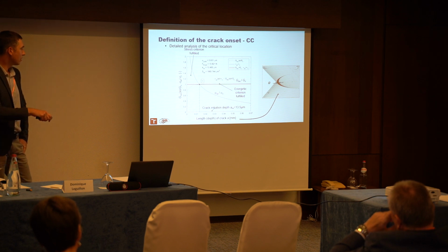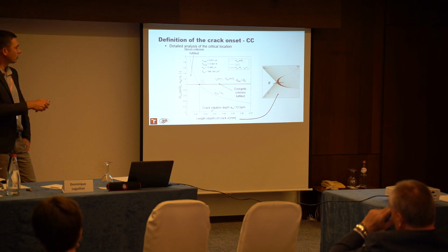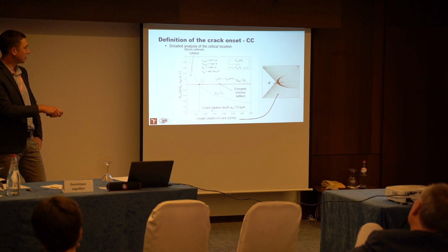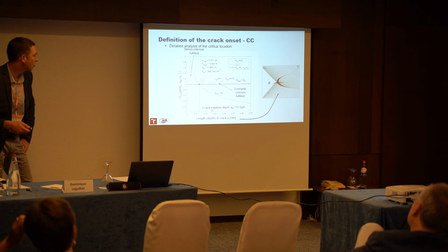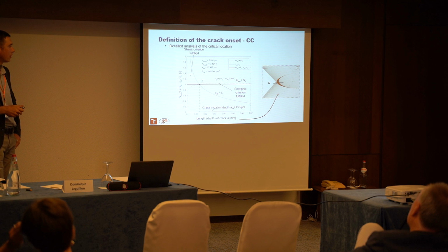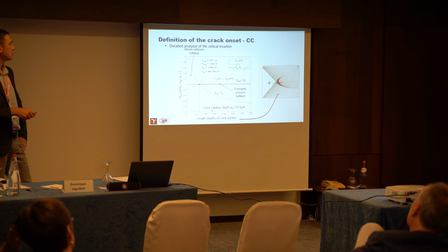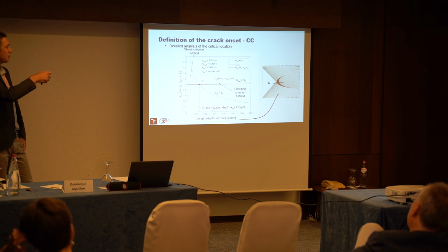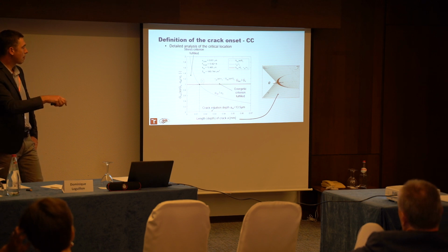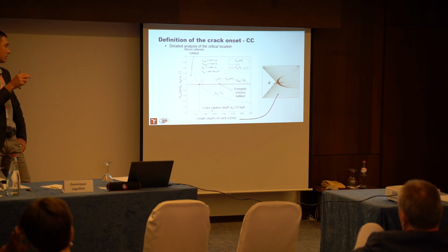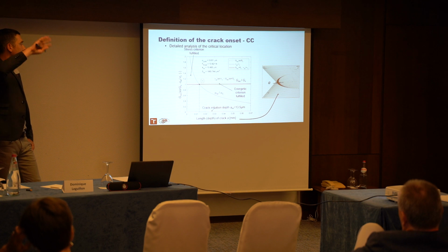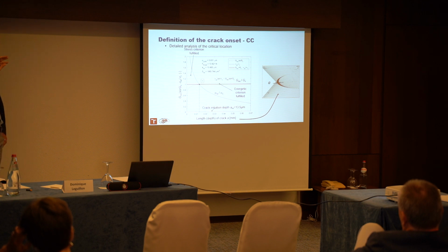So in fact, we can say now that if the stresses in this depth, which is now around 13.5 microns, exceeds the strength of the material, the sigma c, then we can expect that the crack will initiate at this location. Once the crack initiates, we assume that it will propagate further and break the strut, because there is no mechanism which can arrest the crack or stop the crack.